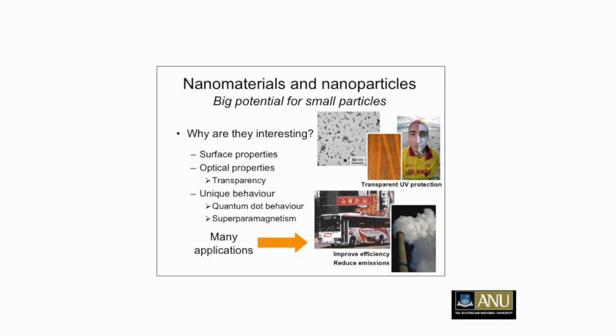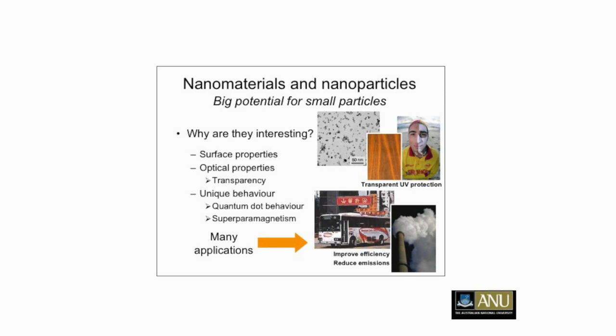In terms of using this, I'll show you lots of applications. I've told you how we make these nanostructures. Here is an example of using nanomaterials or nanoparticles. For example, nanoparticles of zinc oxide are used these days in sunscreen, and they are so tiny that the visible light can pass through, and that means you don't see any light being reflected or scattered back. But they absorb the UV light. That's why when you apply something like this, you don't even see that you applied the sunscreen, because they allow the visible light to pass through. But at the same time, they're doing a good job for you. Whereas if you use micron-sized particles in the sunscreen, you see this zinc cream, and you can see light being scattered, and then you can see the big difference between a nanoscale sunscreen and a micron-scale sunscreen in terms of the light scattering properties.